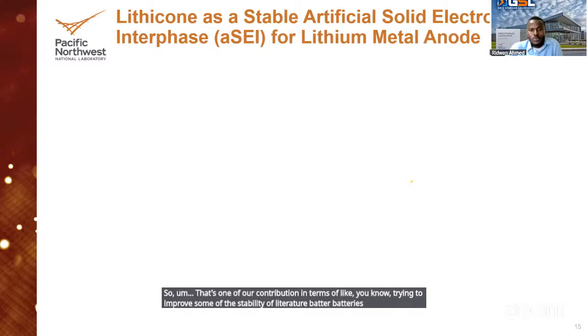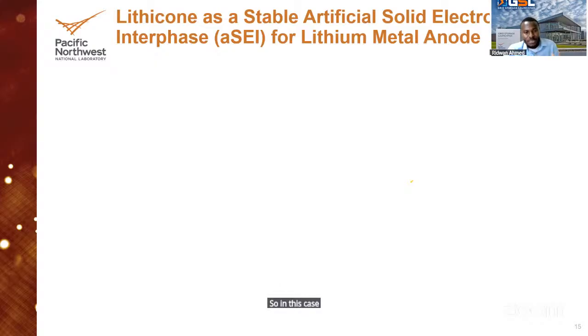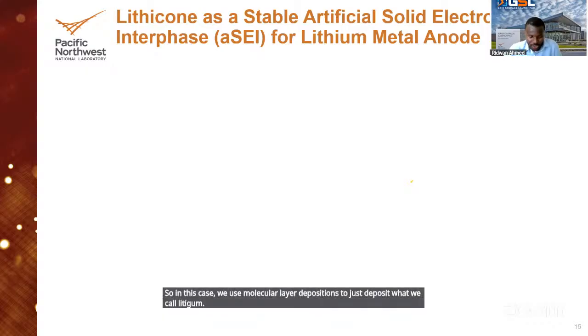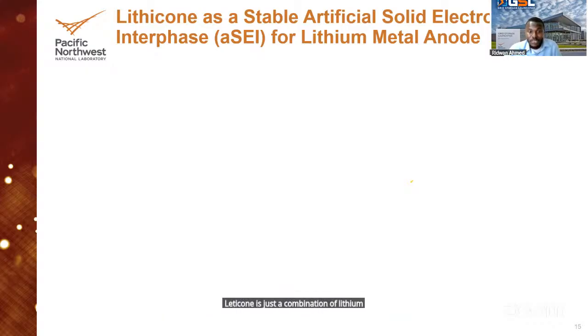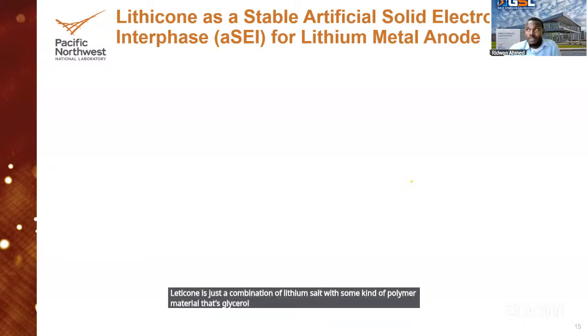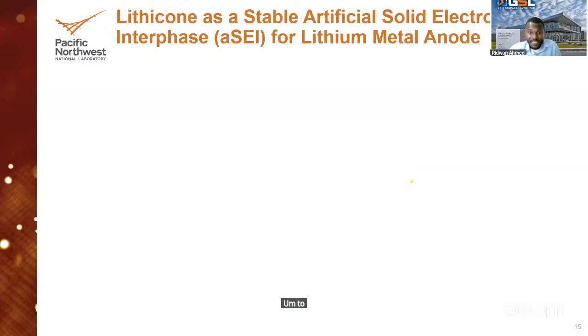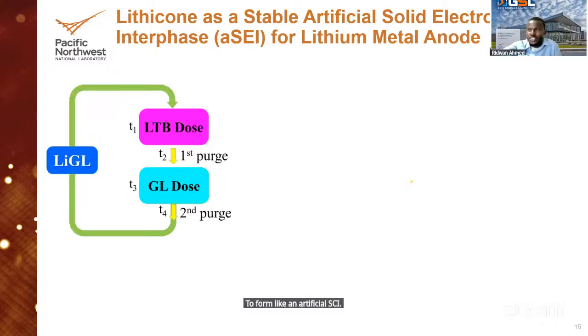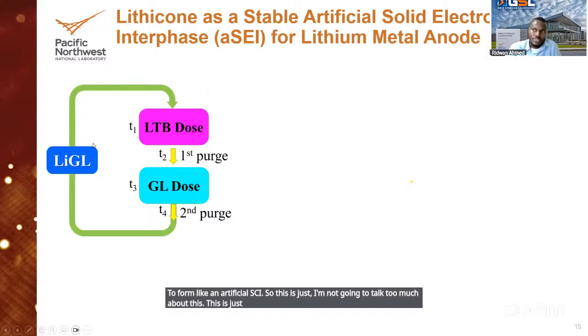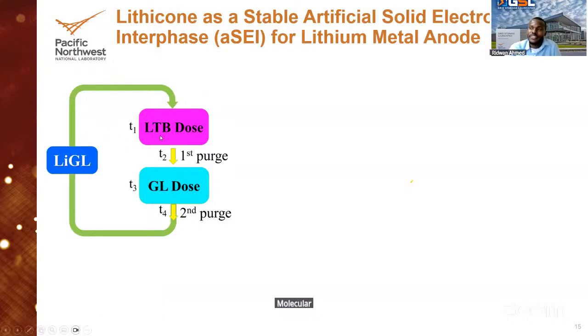So this is another contribution we made, where we try to use a different material and a different method. In this case, we use molecular layer deposition to deposit what we call lithicone. Lithicone is just a combination of lithium salt with some kind of polymer material, glycerol. And so we use that to form a layer on top of lithium metal, like an artificial SEI. I'm not going to talk too much about this. This is just the molecular layer deposition process.